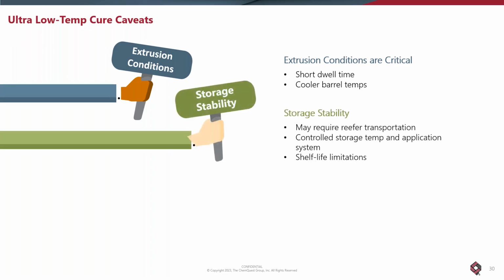Storage stability, it's something you've got to watch. When you start driving down the melt point, the T sub G, you're flirting with 50 degrees Celsius as a T sub G. You've got to watch your transportation, you've got to watch your storage and your application system conditions. So it's just something you've got to look at. Thermosets in particular, they may advance in the solid phase if they're exposed to high ambient temperatures. So it's something you really have to pay attention to with handling these types of chemistries.